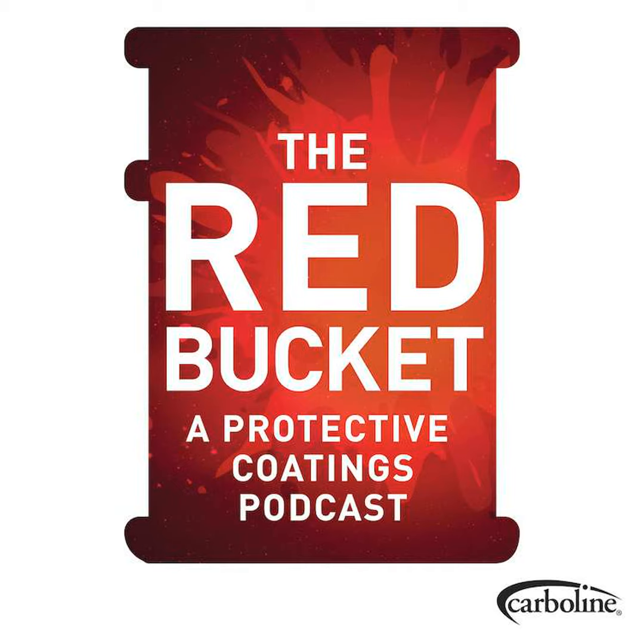What I typically see during inspections is the service that tank car is subjected to. The loading, the unloading, and the stress that the coating goes through. Typically, to get that molten sulfur, it's heated to about 280 to 300 degrees Fahrenheit. So that's the stress that the coating is going through, is what I've seen.